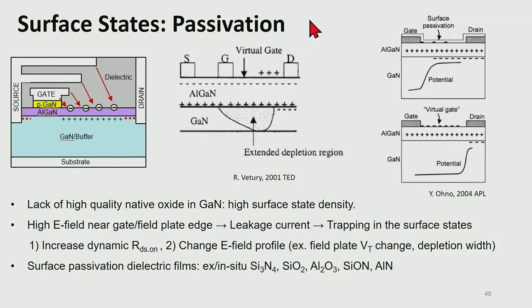So if this virtual gate effect is severe, it can also change the electric field profile completely. If you see this right figure, with negligible electron trapping, the electric field peak is formed near the gate field plate edge, and most of the voltage drop also occurs in this region. But once a severe virtual gate effect happens, the depletion region is expanding, and the electric field peak is now formed near the drain edge. So to suppress this surface trapping mechanism, we obviously need a high-quality surface passivation technology.